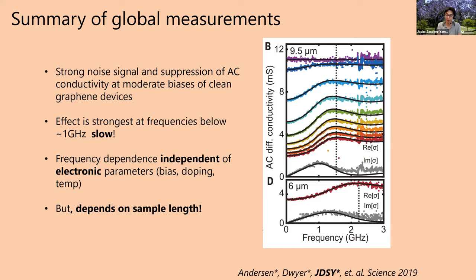The effect is strongest at frequencies below a gigahertz. And as far as electronics are concerned, gigahertz is actually a pretty small frequency. And this frequency dependence is independent of electronic parameters. So it doesn't matter how much voltage we apply, doesn't matter how we dope the material, doesn't matter the temperature, but it does depend on the sample length.